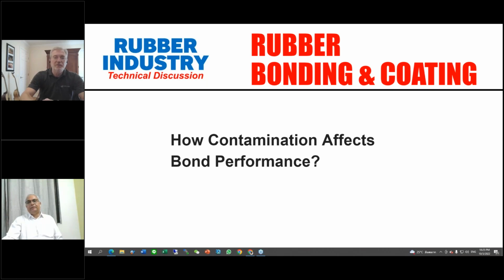That's a really good point. Every coating process must start with a clean surface. I think Ravi did a great job in his presentation on dry lubricants. Absolutely, about demonstrating the importance of cleanliness. Obviously, if there's contamination on your surface, when you go to bond to it, you will bond to the contamination instead of bonding to the surface. So surface cleaning is extremely important, and that applies in both the bonding and overmolding applications and also in the dry film lubricants. I spent less time talking about surface preparation, but it's extremely important. If your parts are dirty, your process will not perform and give you the outcomes that you're looking for.